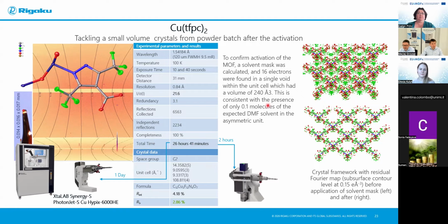And if you have a proper full resolution data set, you can do more advanced structure analysis than just seeing the structure. For example, here you want to check how good the activation was. We generated what are called difference maps, showing what the model describes versus what's inside the crystal, and we see some leftovers, these green blobs of electron density. We were wondering, is this still our DMF solvent or something else, maybe water. So we used what is called a solvent mask, which allows you to calculate this, and we proved that this is just nothing, and the MOF is fully activated. But you should remember that very small crystals, barely visible under a microscope, can be used for single crystal analysis.